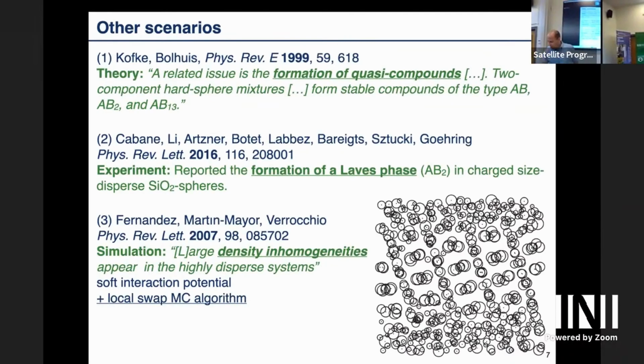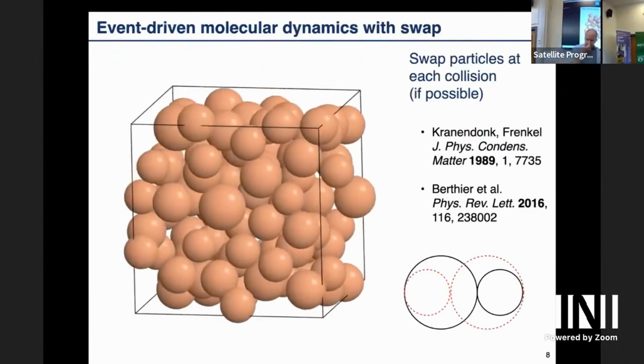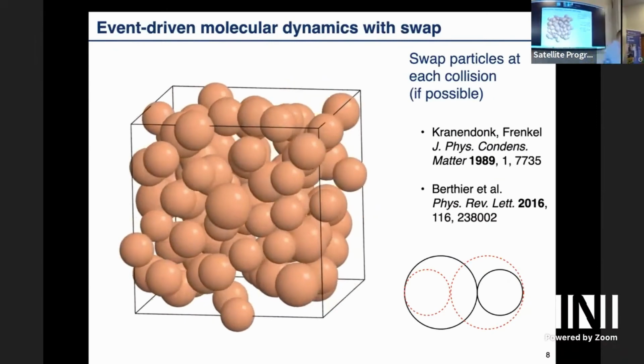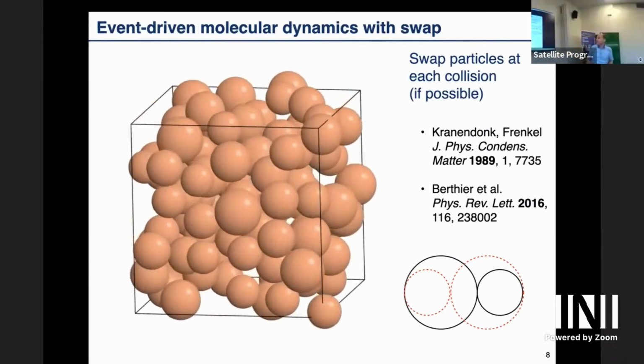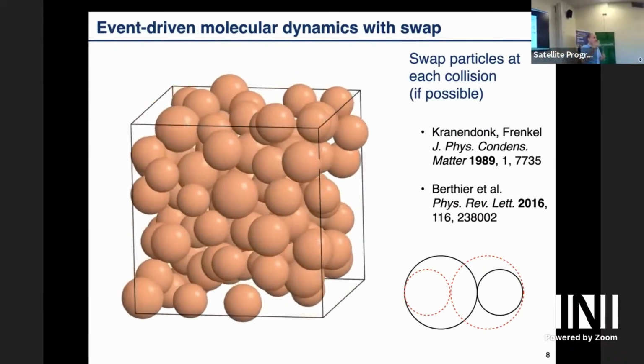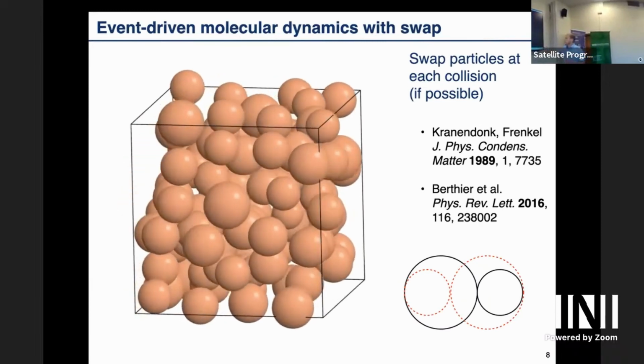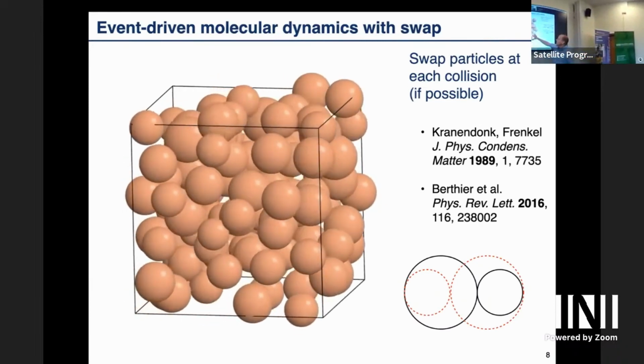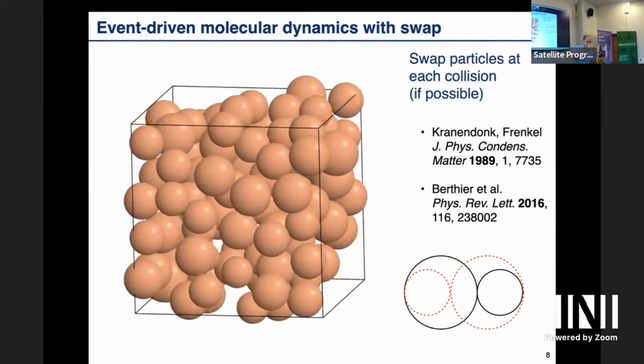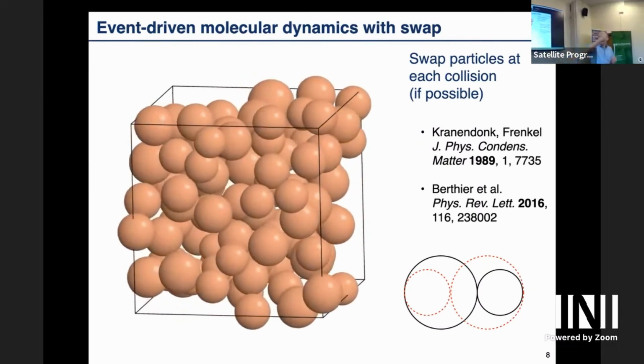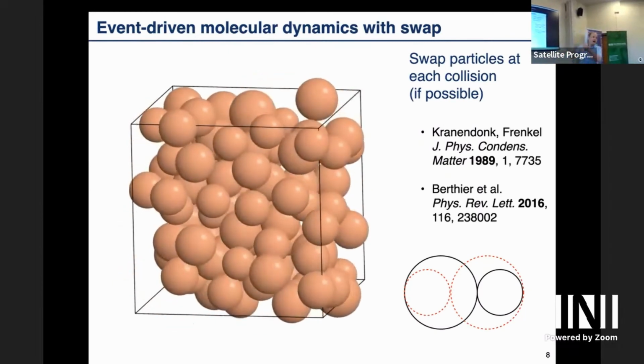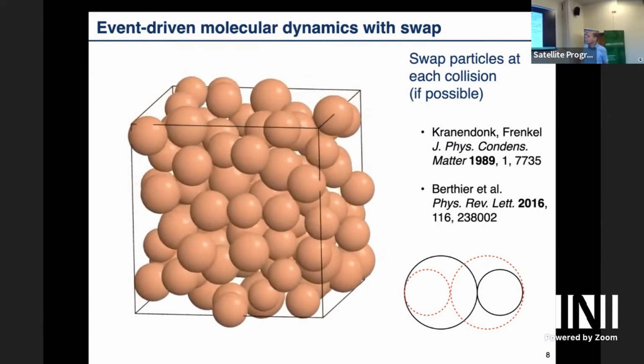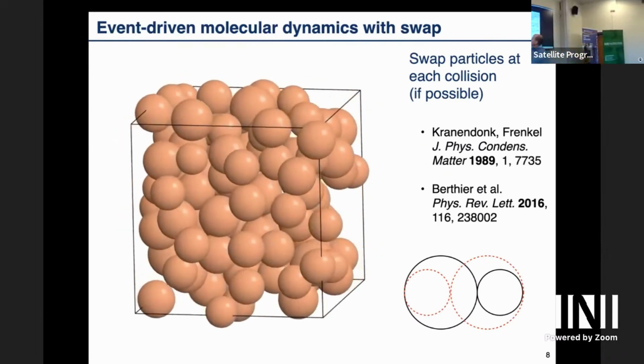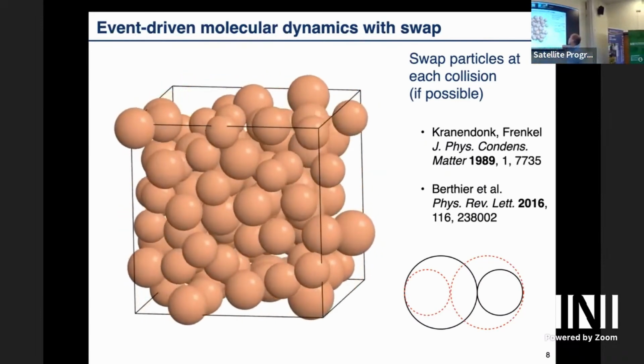And that brought me to the idea, well, let's do something like this, but a couple swaps with event-driven MD. So event-driven MD is essentially the same, it follows the trajectory of the particles. So you see here a very slow simulation where the particles move ballistically until they collide. And then when they collide, you try to swap the radii of the two spheres. That's why you see here the radii getting larger and smaller all the time.